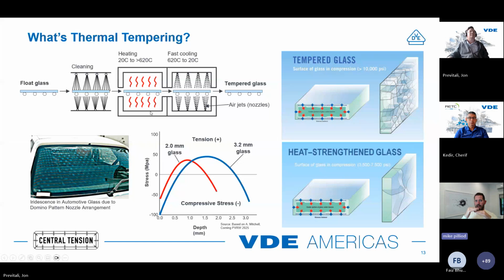It's still keeping its flatness, and then it goes into a fast, rapid cooling on the surface of the glass. And what happens is that the surfaces freeze, and the inner meat of the glass continues to shrink, thus pulling the surfaces into compression. So this is a fundamental thermal expansion property of the glass, and it gets heated up. The surfaces get frozen, for lack of a better word, with air pressure, and then the middle of the glass continues to shrink, pulling everything into compression.